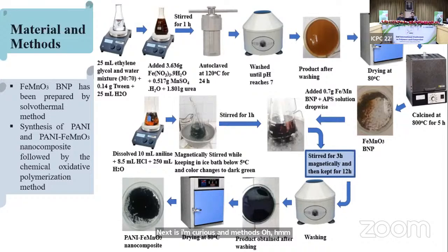Nanoparticles have been synthesized by a temperature-controlled solvothermal method, and then they are incorporated with aniline by the chemical oxidative polymerization process using HCl and APS as an oxidizing agent. There is a detailed pictorial representation in this slide. It started with adding a 30-70 ratio of ethylene glycol and water, and Tween is added as a surfactant to stabilize the precipitates. They are magnetically stirred, and the precursors of iron and manganese were added with the capping agent,